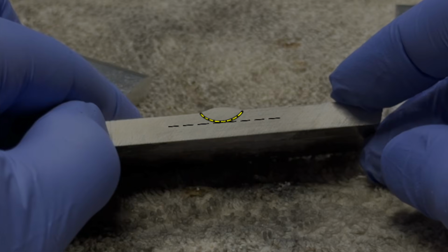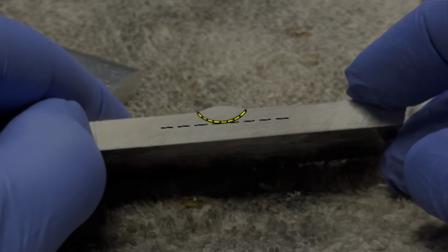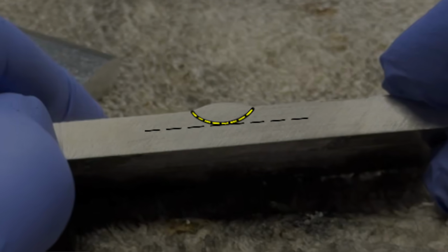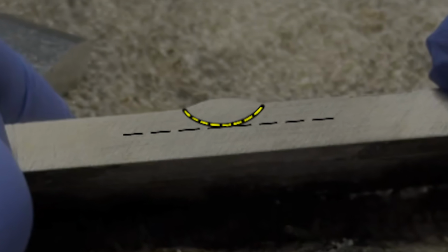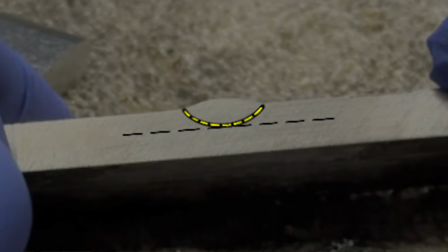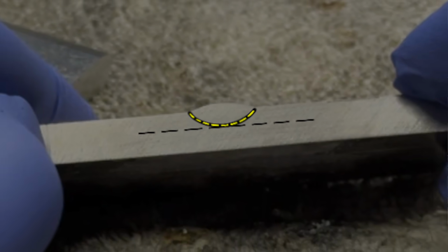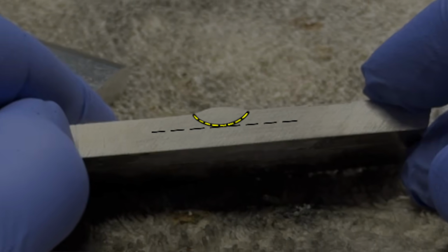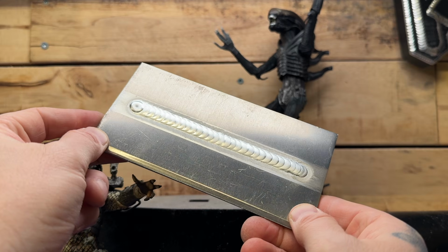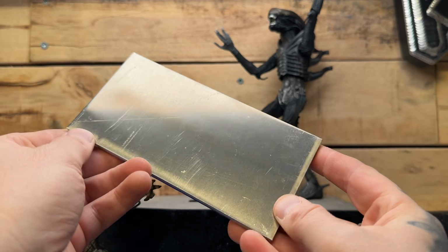Pretty sweet, huh? This is going to teach you a lot more about your arc control as well as the settings and the setup that you are welding with. You want to be able to take a look at one of these cross sections here again, and you want to be able to see that you have been able to knock the heat into this base material a little bit to achieve penetration, even though we didn't see any on the other side, right?